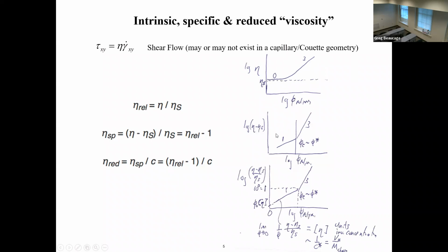So if you subtract off the solvent, like a background subtraction with the scattering, then you can see this power 1, which means that you have an additive effect of the polymer. It means that the whole polymer is acting like a sphere moving through the fluid, as if it was a sphere. It means it's non-draining. So it's draining and non-draining. If the chain is non-draining and it's acting like a sphere, then you get this linear addition.